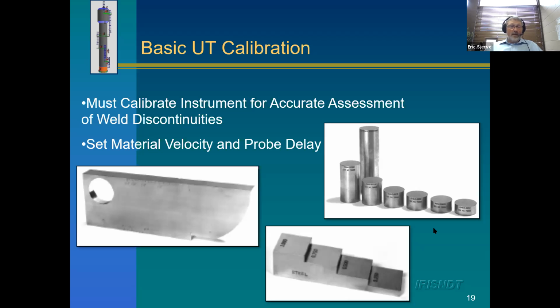So we know what the thickness of the pressure vessel is, 10 millimeters and not 20, because we need to calibrate it. So that's the first part of a calibration when you do ultrasonic testing: you have to set the material velocity, and the probe delay is how much time the sound takes to get out of the ultrasonic transducer, because you don't want to take that into consideration when you do the inspection. You just want to know the material you're inspecting, not the probe. So that's a y equals mx plus b type calculation, and that's the first part of a calibration when you do ultrasonic testing.